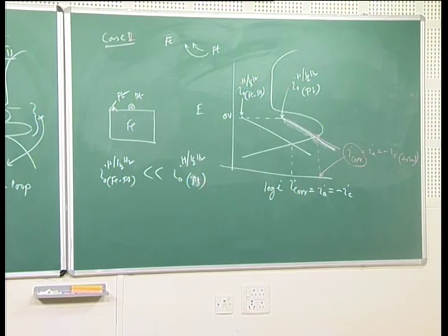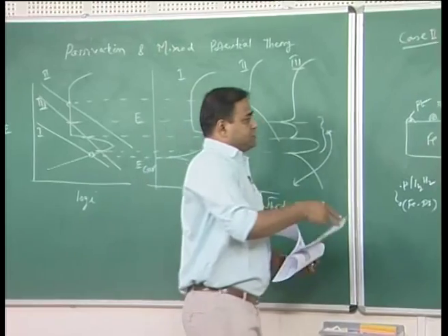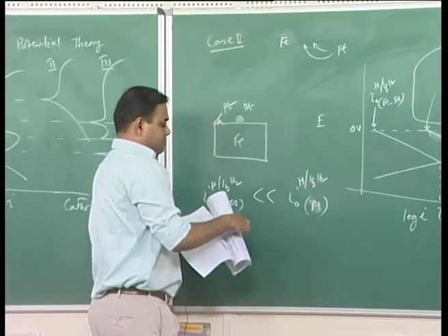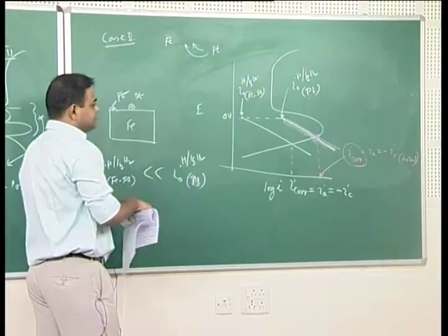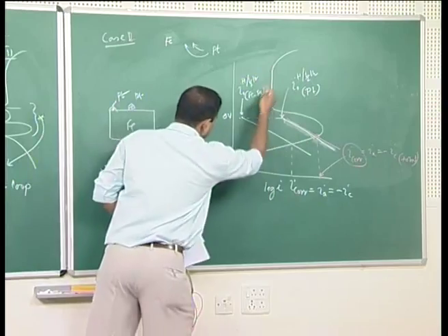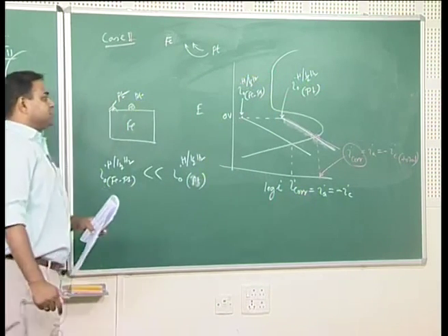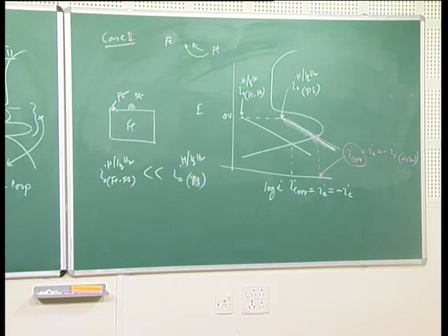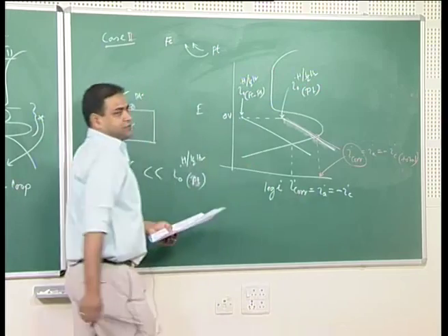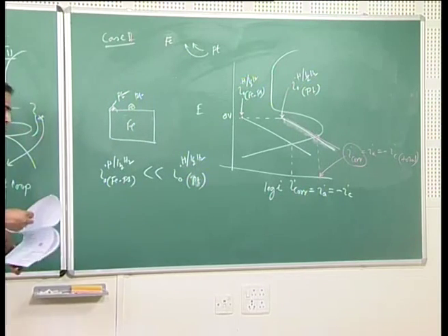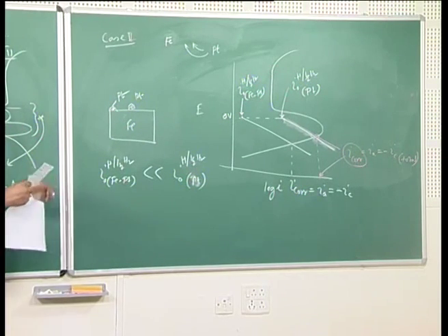So, that means depending on the position of this cathodic polarization start point and the polarization curve for the active passive metal, noble metal addition can be advantageous, it can be disadvantageous. So, in case of iron, we should not add platinum, because if we add platinum, we are going to increase the corrosion rate.